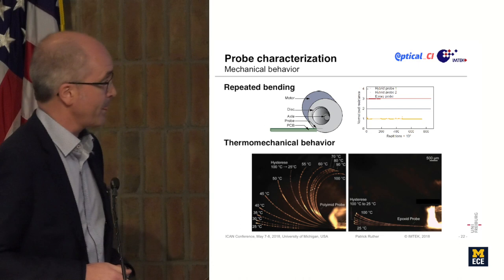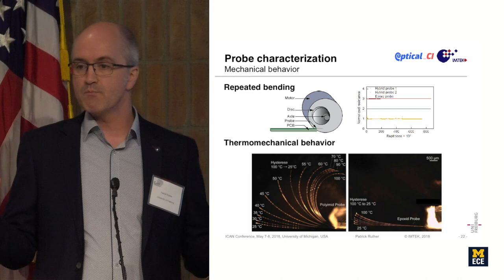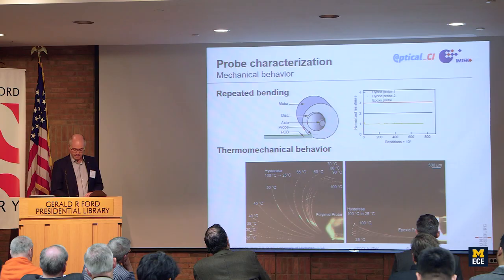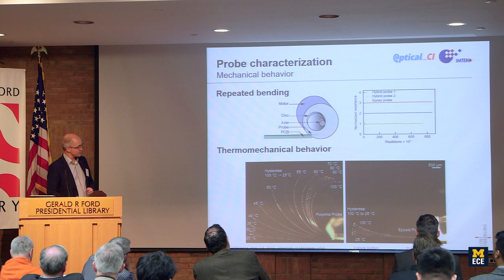In contrast, the purely epoxy probe shown here stays more or less straight. Little thermomechanical stress in the probe itself.